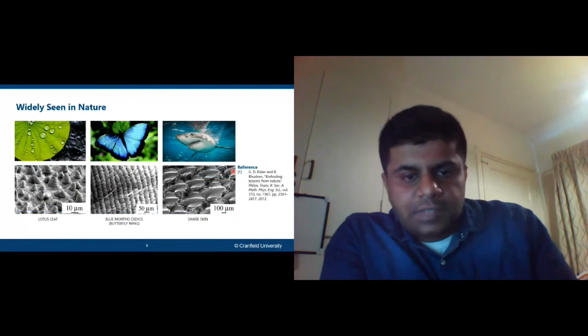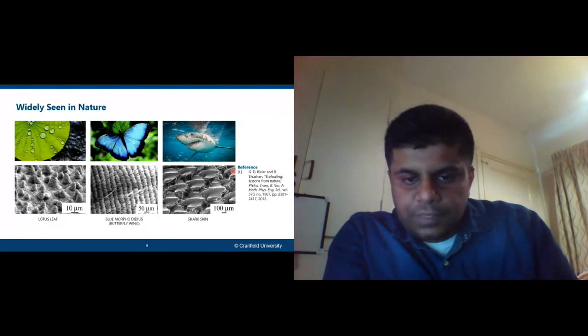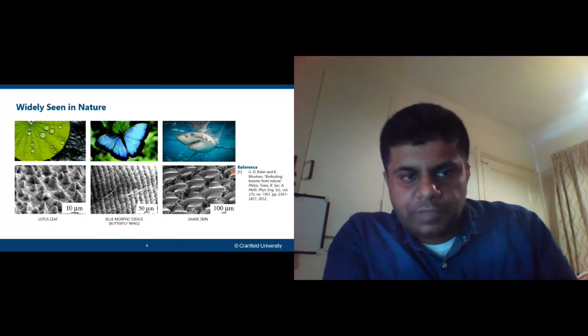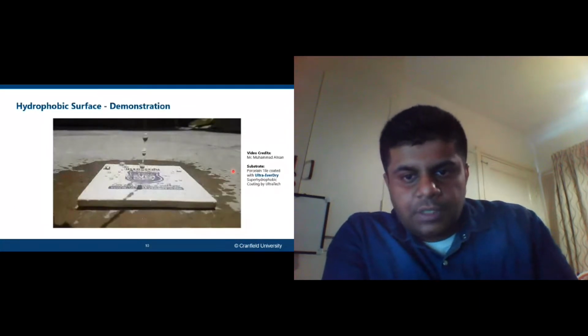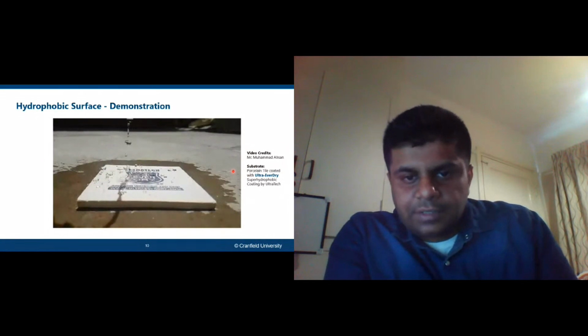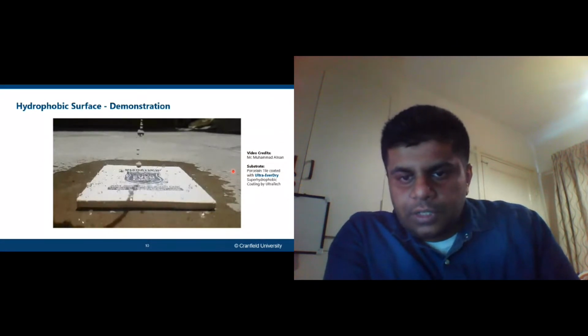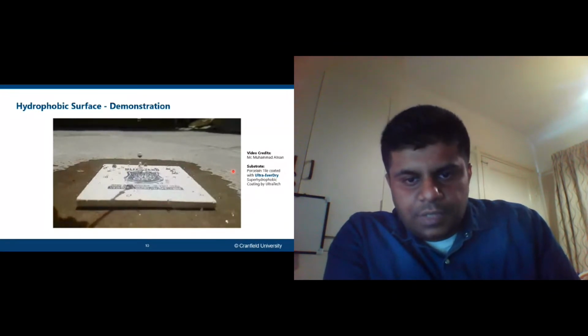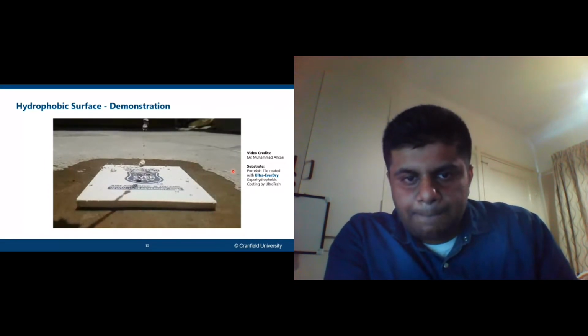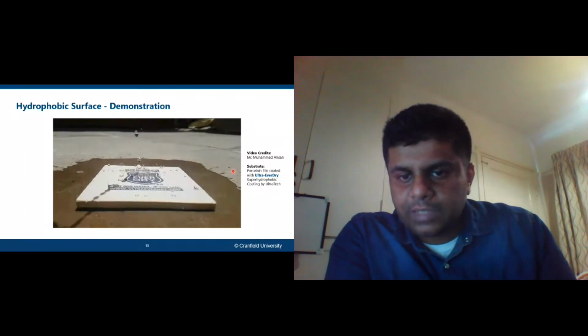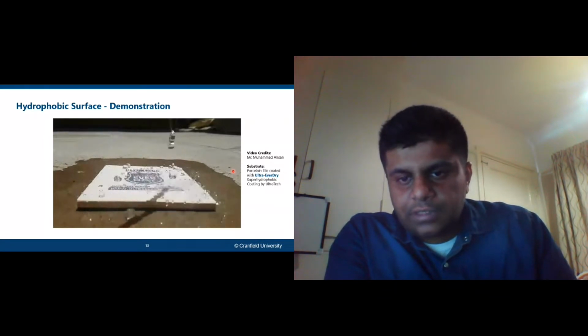So as we discussed, this is an application of biomimetics. This behavior is widely seen in nature, where shark skin, blue morpho butterfly wings, and lotus leaf exhibit this behavior to their fullest. Here we also see another example that we conducted ourselves. This is a small experiment on a super hydrophobic coating that we received from Ultra Ever Dry back in Pakistan. As you can see, water does not stick to the surface at all and just keeps on flowing. If you maximize this to a certain level, you will also see the water droplets bouncing off the surface, which is known as the bouncing drop test, commonly conducted for these surfaces.